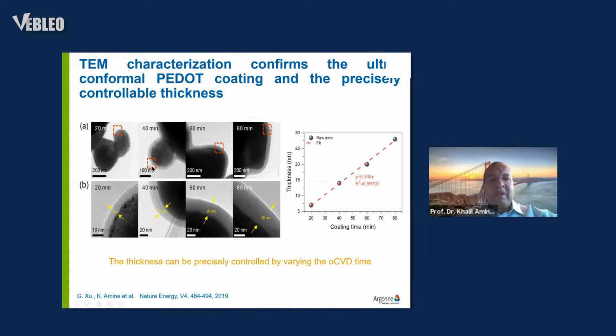For example, these are different coating times, basically exposing the mix to 100 degrees C in the reactor. And we can see clearly that in all cases, we form a very conformal coating. The best performance we got is at 60 minutes. We get a 20 nanometer coating that is very uniform. This is outside the particle.